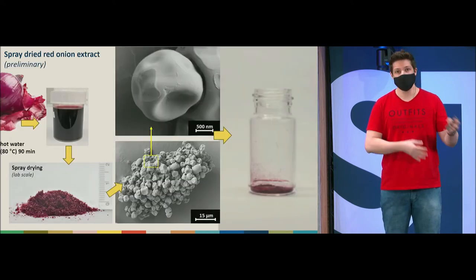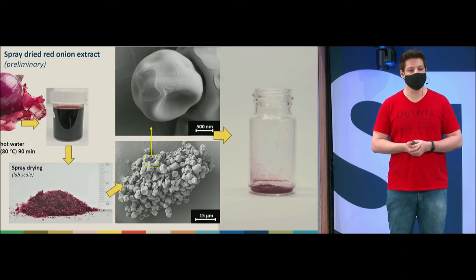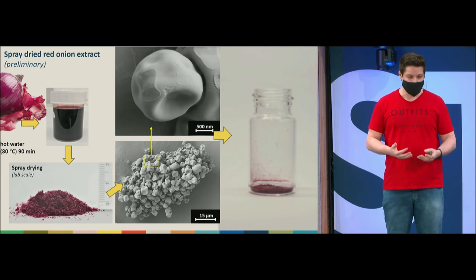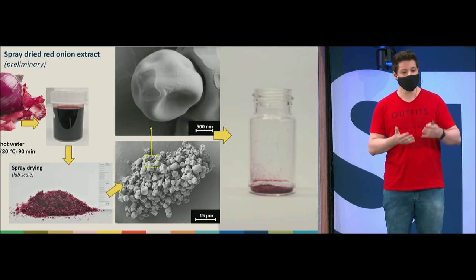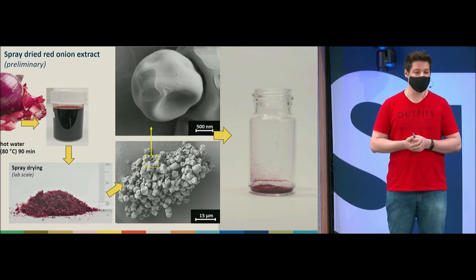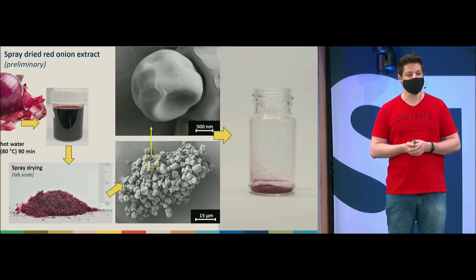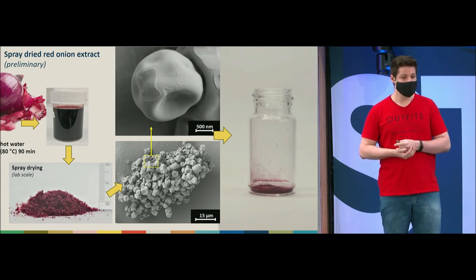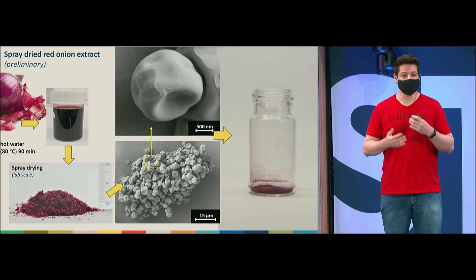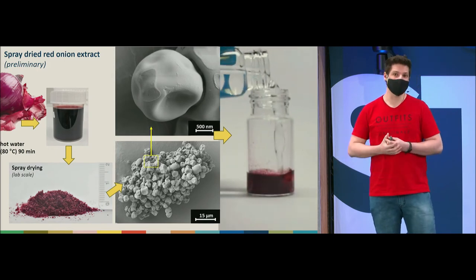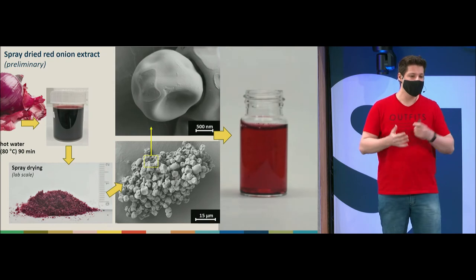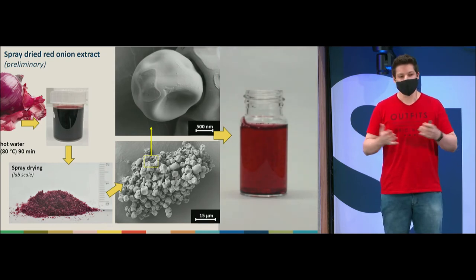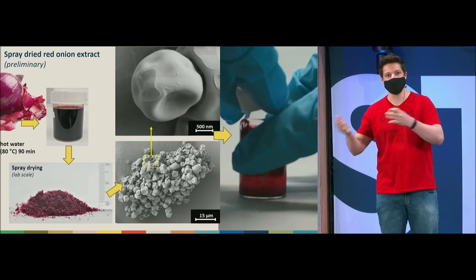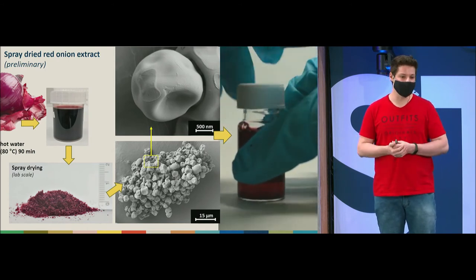And our initial results using onion extracts show that the technique is very suitable for our purpose. We get this nice purple powdered material, which is composed of small particles, as you can see in the pictures. And the particle size is important because they will also help to redisperse this material according to your needs. So now if you want to have 5 grams of material, you just pick 5 grams of the powder. You don't need to work with 500 milliliters or higher amounts of water.